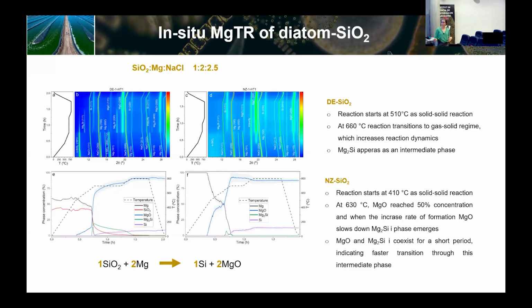Also, something we saw was the formation of a magnesium silicide phase as an intermediate phase that then goes away. But in our case, we have it as a reaction product, which was very strange because it should not be.